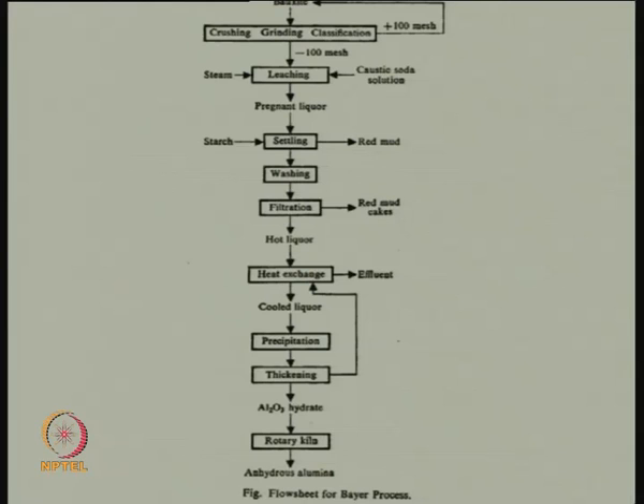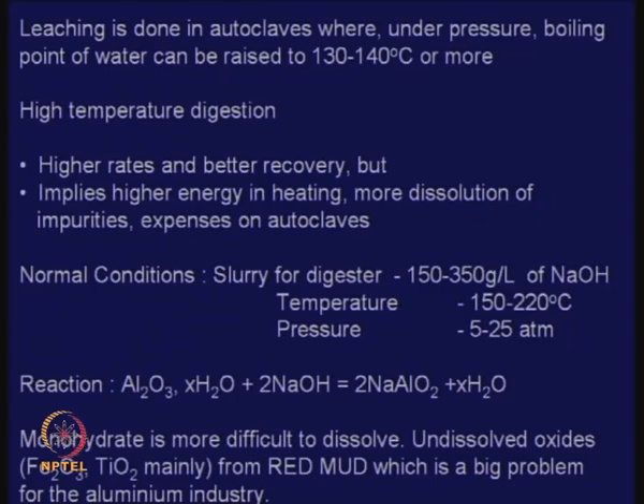I hope you have understood that you have taken bauxite, you have leached under pressure using caustic soda, and you got a liquor. The insolubles form red mud, the liquor is cooled, heat is recovered, and from the liquor you do incomplete precipitation of alumina, and that alumina under a rotary kiln would finally do this.